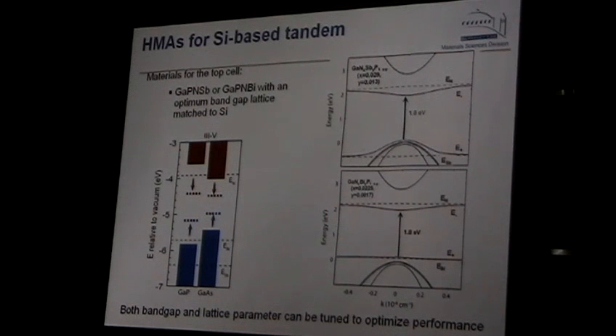So there is some effort right now to try to make this tandem, which would be lattice matched to silicon. And so I guess my message is that highly mismatched alloys are a new class of materials which really give you great flexibility in manipulating band structure and hopefully using it for different applications. This basically shows what the band structure would look like, and with band gaps we can create a band gap of 1.8 electron volt.